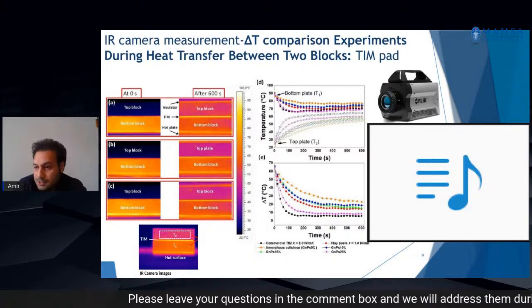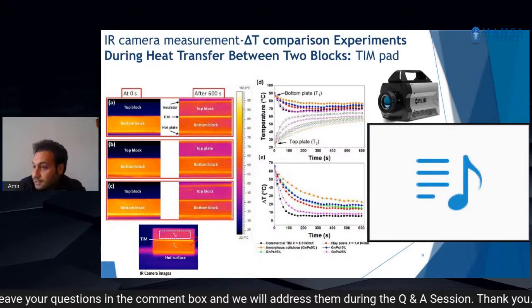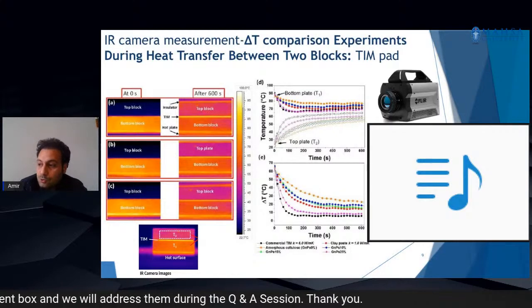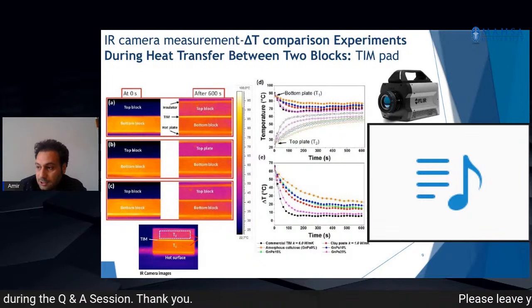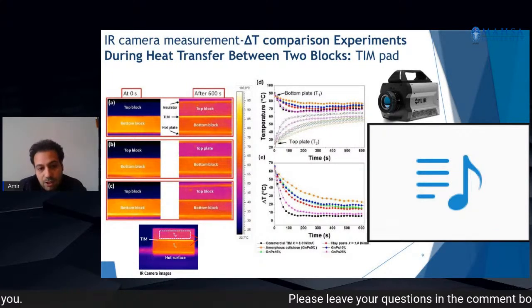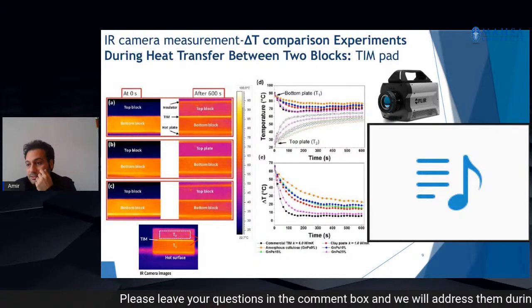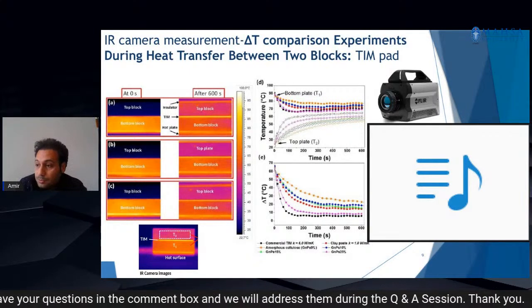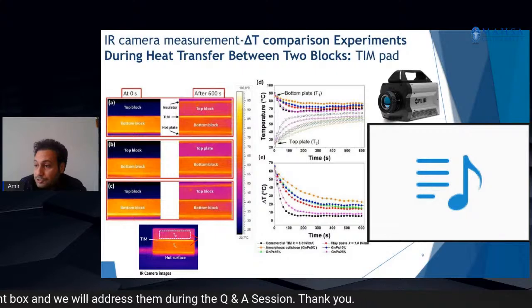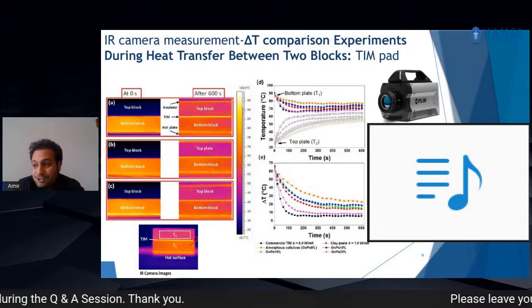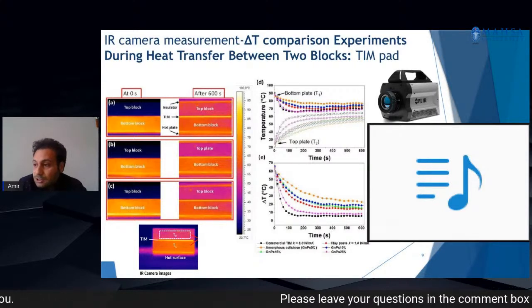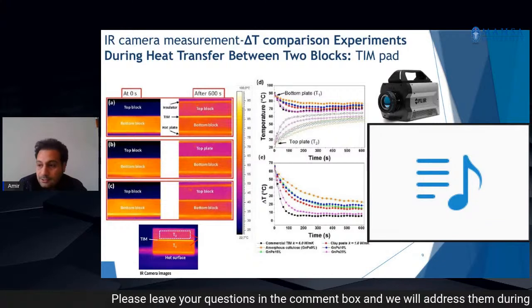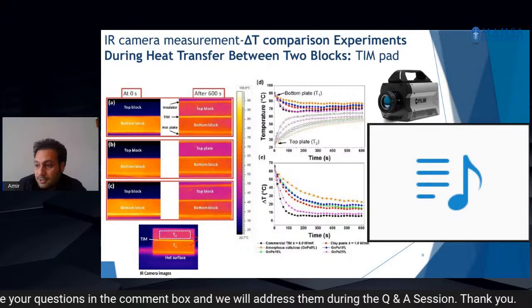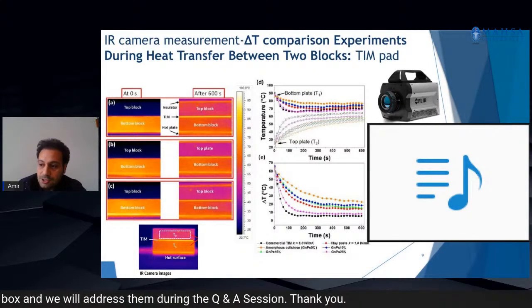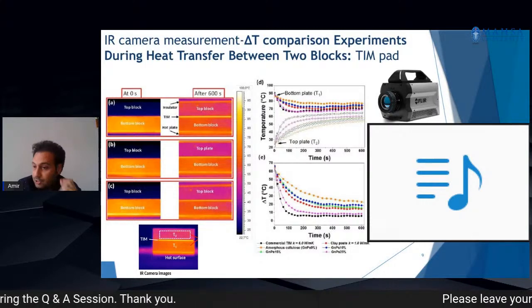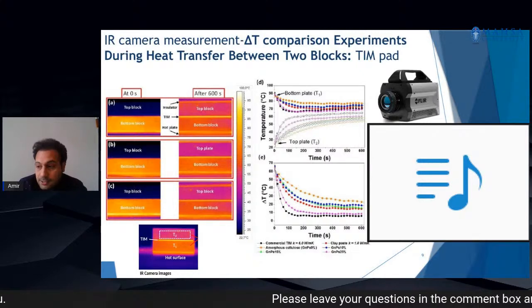So this is the representative sample of the data collected, the average temperatures T1 and T2 from the experimental setup and infrared thermography. How we collect the data, I will explain. After placing the prepared sample between the two blocks, the decrease in average temperature of the bottom steel block and the increase in average temperature of the top steel block were recorded using an infrared camera. For this, a certain rectangular area near the mating interface in both steel blocks was selected using the FLIR Research IR software to analyze the data.